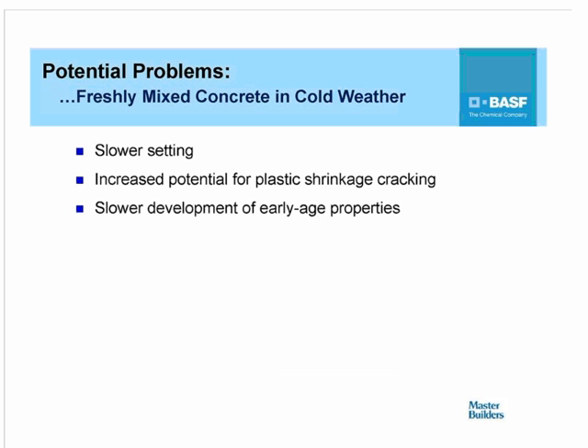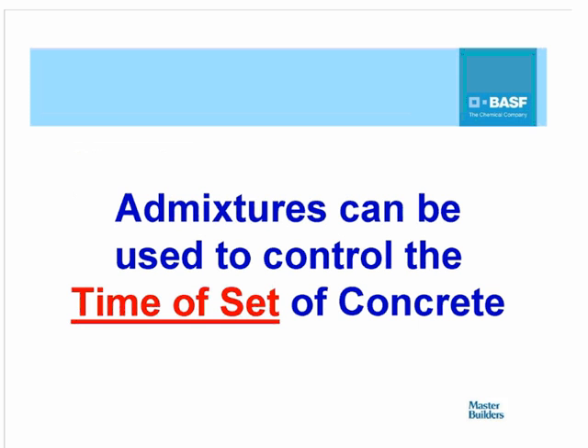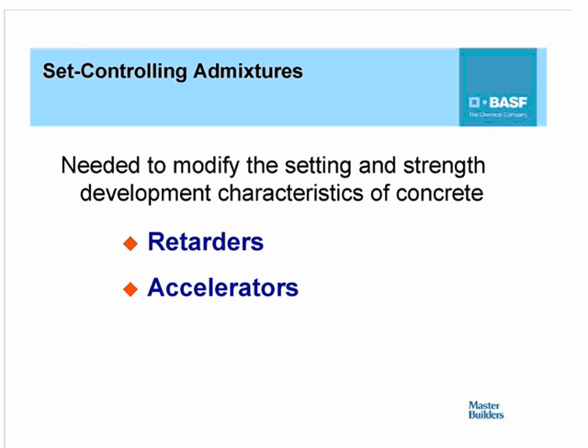With respect to cold weather, the exact opposite tends to happen. The concrete sets slower, and this can increase the potential for plastic shrinkage cracking if the surface of the concrete in flatwork is not protected. In addition, strength development, especially early age strength development, will tend to be impacted as well. As a result, we use admixtures to control the time of setting of the concrete. These admixtures are basically called set control admixtures, and they're used to modify the setting and strength development characteristics of the concrete. These fall under two different groupings: retarders and accelerating admixtures.